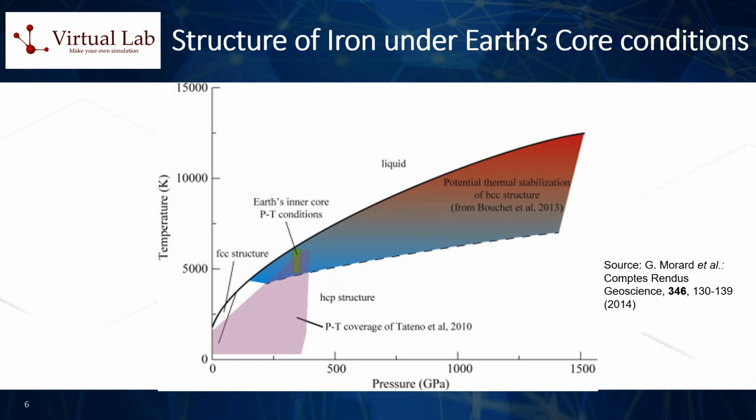Recently, a growing amount of both experimental and computational evidence has suggested that the BCC ambient structure might again become stable at the high pressures and high temperatures conditions found inside the Earth's core, especially when we consider iron to be more realistically alloyed with small quantities of other elements, such as the aforementioned nickel and light elements. In practice, it is likely that iron exists in a mixed phase combination of both the BCC and HCP phases simultaneously inside the core, including the presence of even more complex phases such as a double HCP, or DHCP, phase.